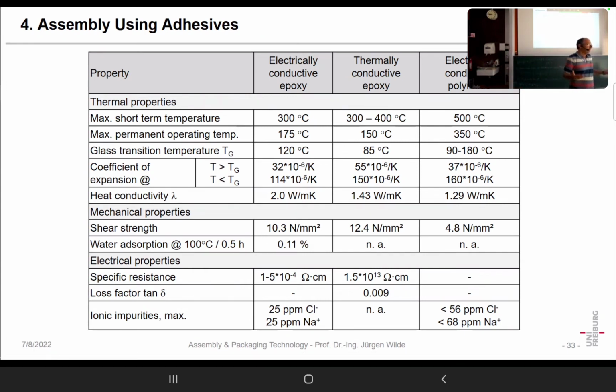Epoxy, of course, has a significantly higher CTE, maybe 60 or so if it's not filled with silver. On the other hand, by going beyond the glass transition temperature, typically in polymers, the CTE increases by a factor of 3 to 4.